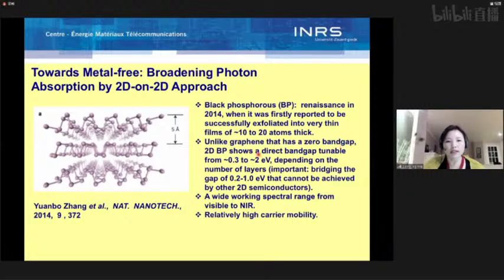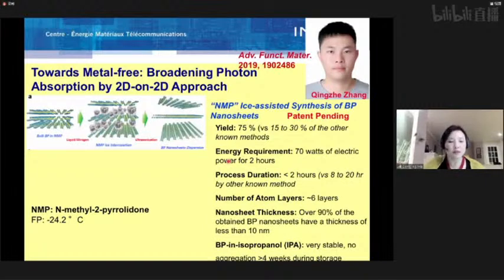It shows a direct band gap tunable from 0.3 to about 2 electronvolts, depending on the number of layers. And it has a wide working spectral range from visible to near infrared, and also relatively high carrier mobility. So all this predicts that BP can be a very interesting photocatalyst. But before we can use them, we need to overcome some challenges.